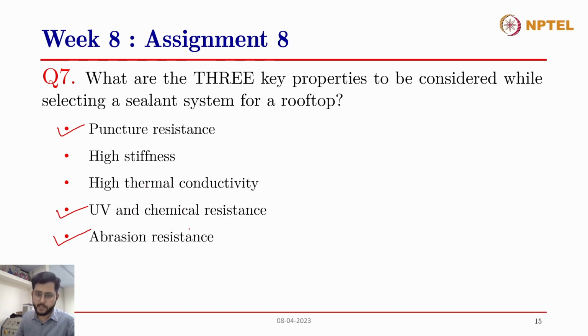Then comes the UV and chemical resistance. Yes, the sealant system needs to have a good UV and chemical resistance. UV resistance needs to be there because it will be exposed to sunlight, and the sunlight will have UV rays. When these UV rays hit these polymeric coatings, they become brittle in nature, and they tend to break and tear off or peel off from the concrete surfaces, and this is also similar in the case of sealant systems. Therefore they need to have a good UV resistance.